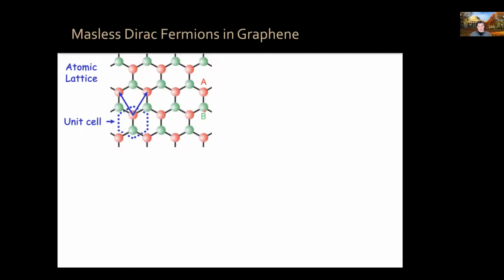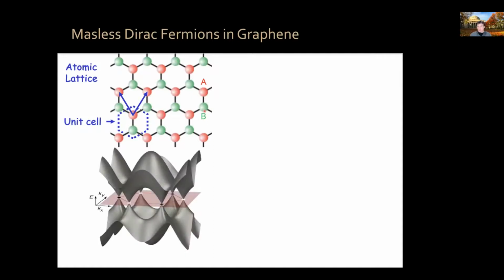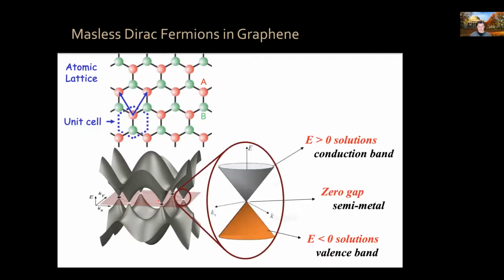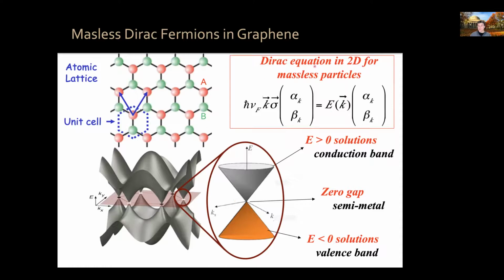Now, one can calculate the electronic structure for electrons in graphene, the energy-momentum dispersion, energy versus momentum in the X and Y direction. And as you can see, this is a very unusual electronic structure. In particular, if you zoom in near the Fermi energy, you can see that the relationship between energy and momentum is linear. So graphene has this linear energy-momentum dispersion that has led to all these comparisons with massless ultra-relativistic particles. In fact, if you look at the Hamiltonian that governs this behavior, it's nothing else but the Dirac equation in 2 dimensions for massless particles.